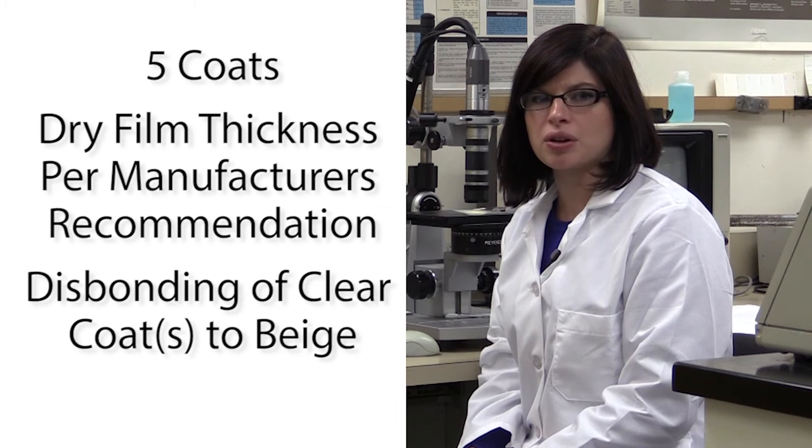The microscopic analysis showed the clear coats were disbonding from the beige, with some beige discoloration on the backside. No evidence of dirt or debris was detected at the failing interface. The microscopic examination also showed foaming through the clear coat in a sample taken from the area near the door.